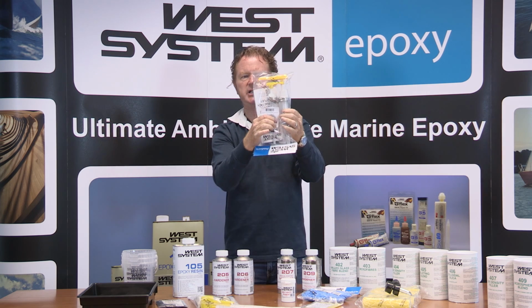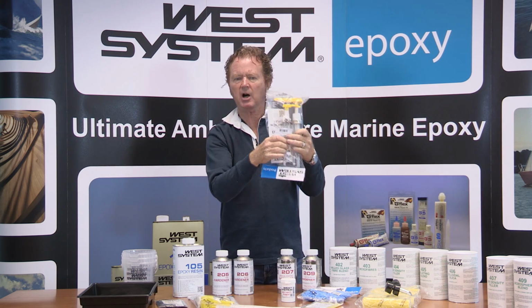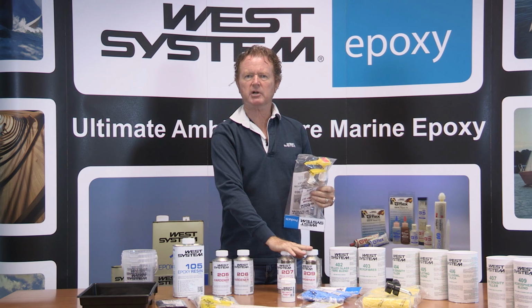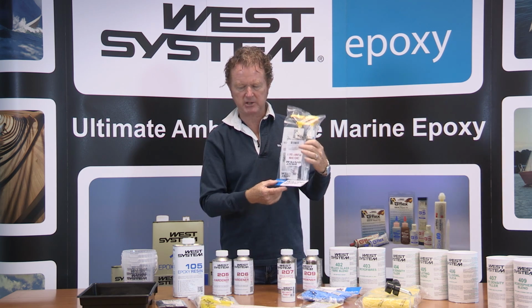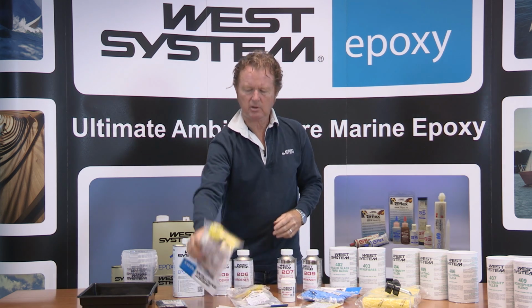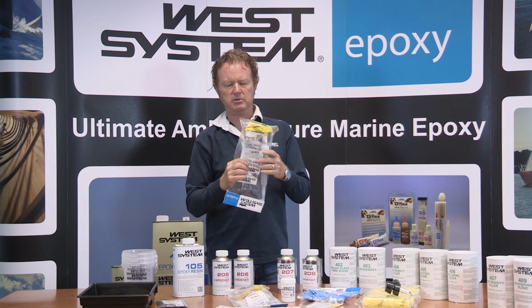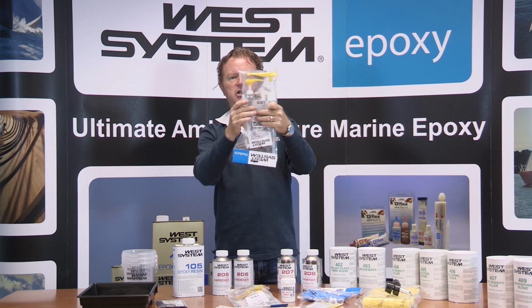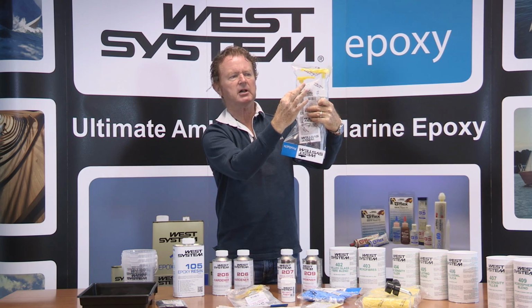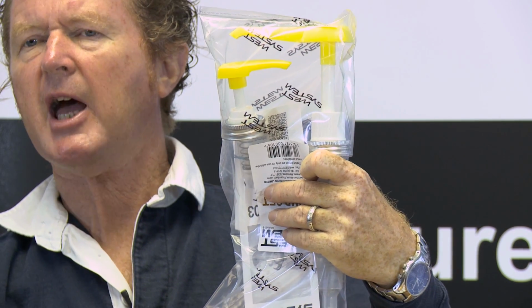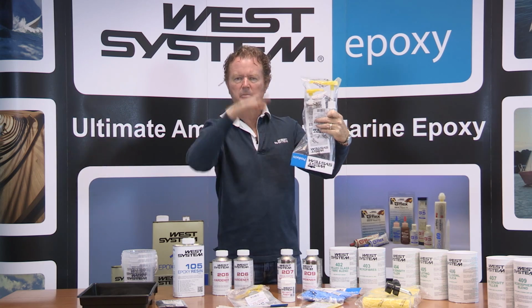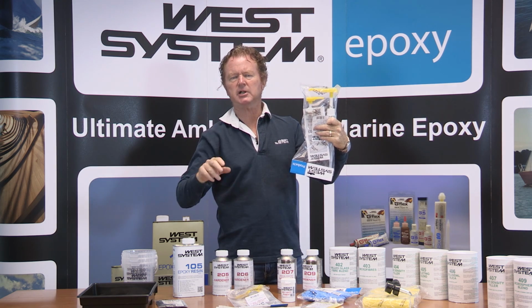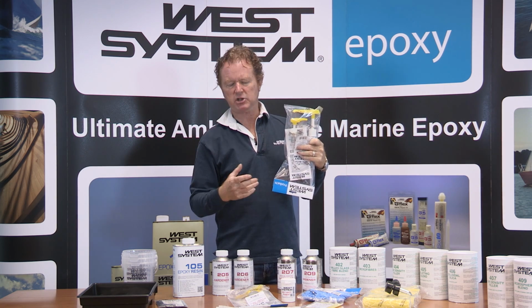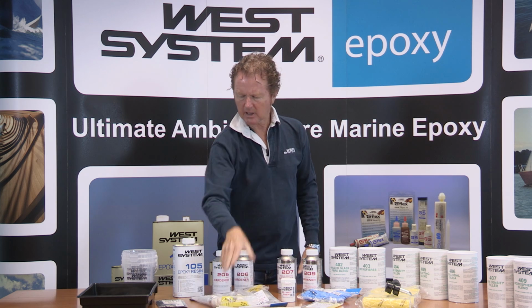They are calibrated as well to give you either the 3-to-1 ratio from a 3-to-1 pump set or the 5-to-1 ratio from a 5-to-1 pump set. You can see quite clearly that the hardener pump and the resin pump have a different stroke to them. So one pump of resin, one pump of hardener gives you the correct ratio.